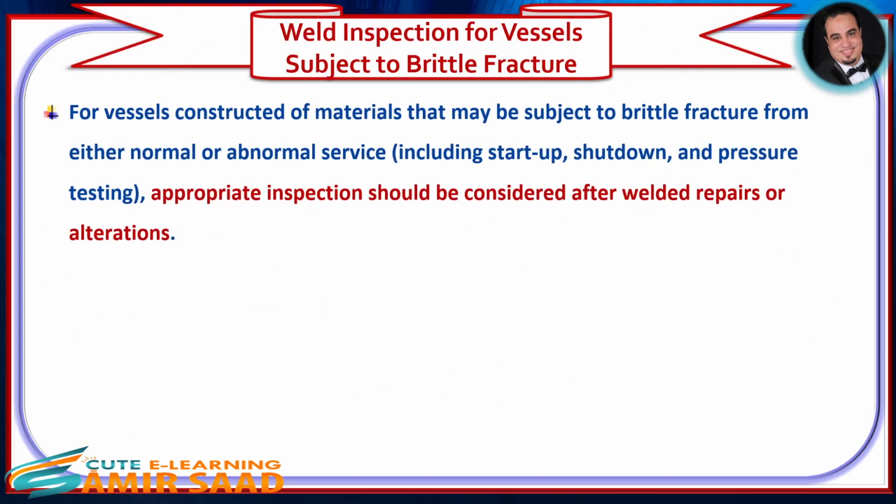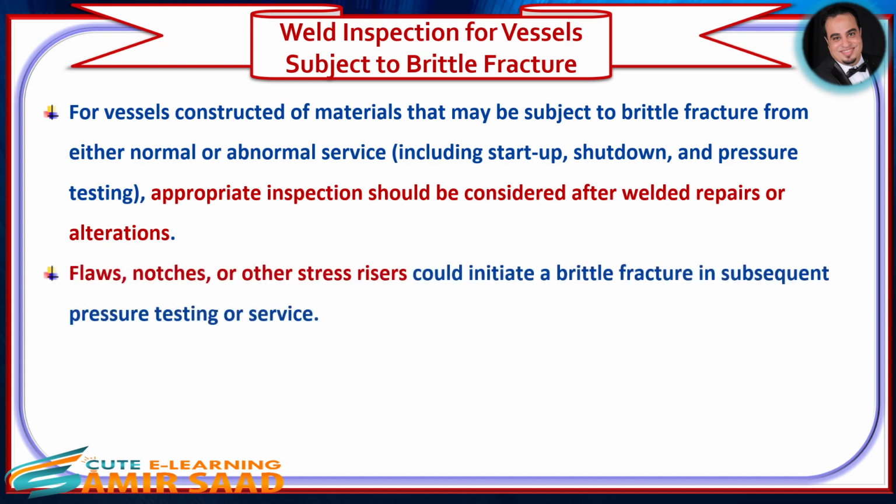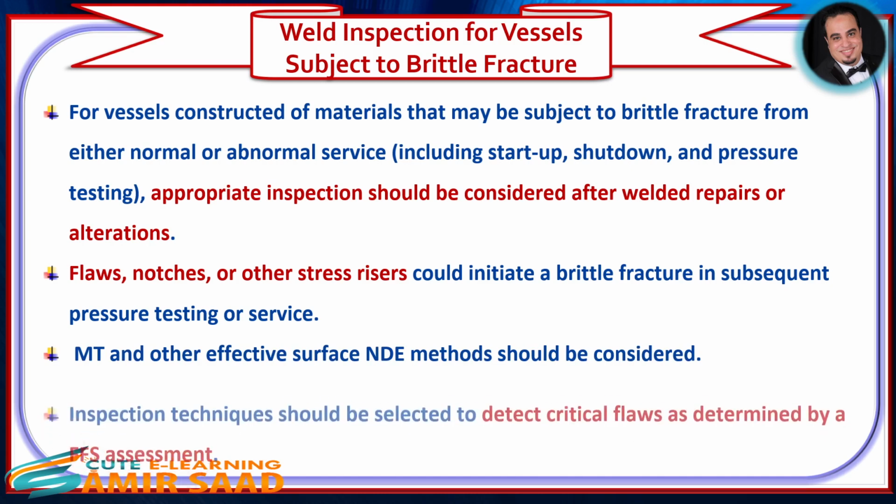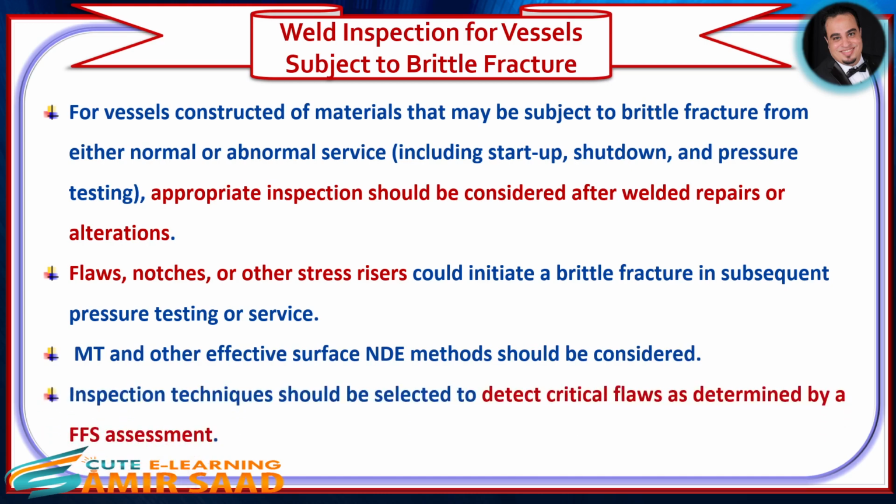Weld inspection for vessels subject to brittle fracture. For vessels constructed of materials that may be subject to brittle fracture, from either normal or abnormal service, including startup, shutdown, and pressure testing, appropriate inspection should be considered after welded repairs or alterations. Flaws, notches, or other stress risers could initiate a brittle fracture in subsequent pressure testing or service. MT and other effective surface NDE methods should be considered. Inspection techniques should be selected to detect critical flaws as determined by an FFS assessment.